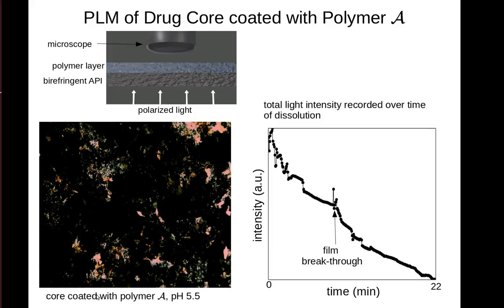The image down in the bottom left is a polarized light microscopy image at the start of the experiment. Since the API is birefringent, the only bright spots that we should see are where we have an optically active material, such as the API. When the API dissolves, it is no longer optically active, and therefore the image goes completely black. To quantify this over the experiment, we can plot the total intensity that we see from the microscopy as a function of time.